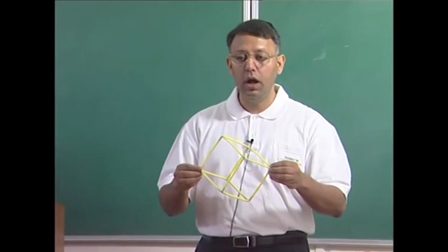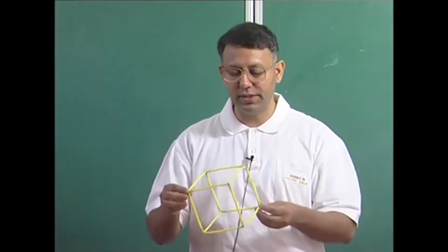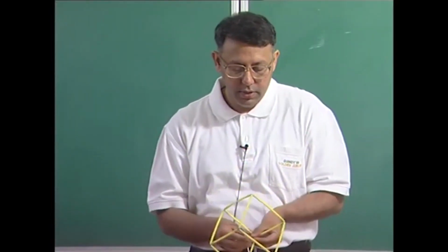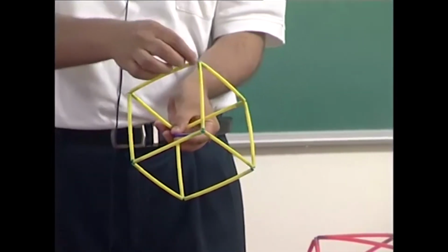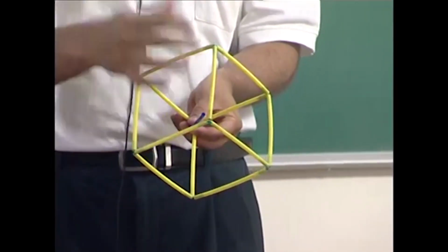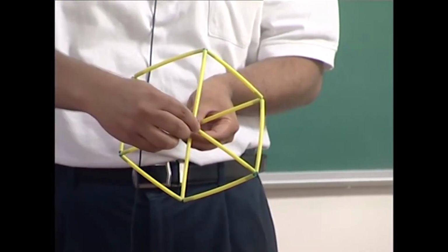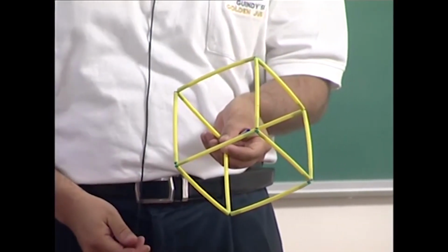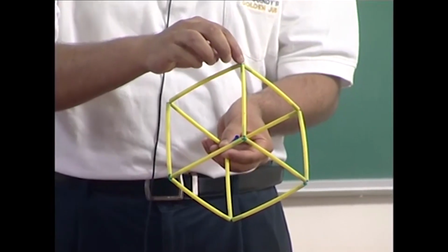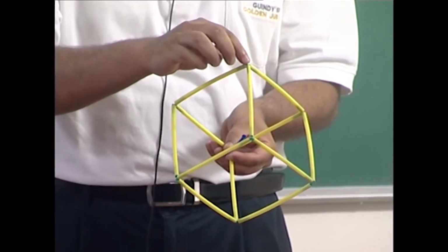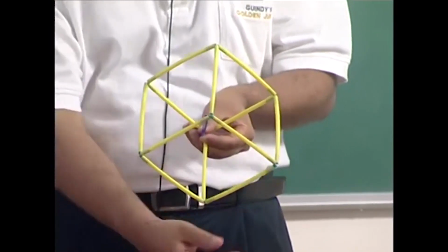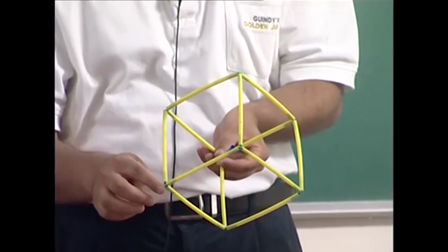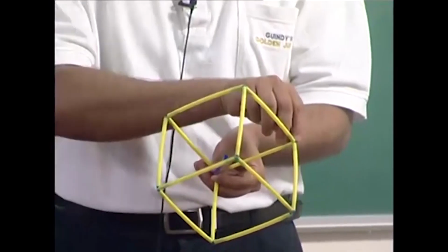Now, let us try to understand where the 3 bar operation is and how we get the 6 points. So, if I consider my cube and my body diagonal, which is passing as you can see here, what does it do? If I start with a general point here, which is one of the vertices of the cube. I have totally 8 vertices for the cube. 2 of them I have taken away by putting my body diagonal line across that, and in addition to that I have 6 more vertices left. So, I can start with any one of those vertices, and when a 3 bar rotation axis acts on this, it will rotate it by 120 degrees, which will take it here, and invert it so as to produce this vertex from that.